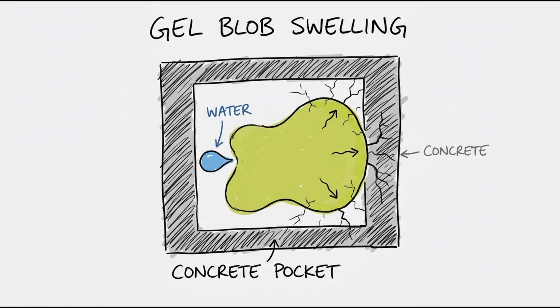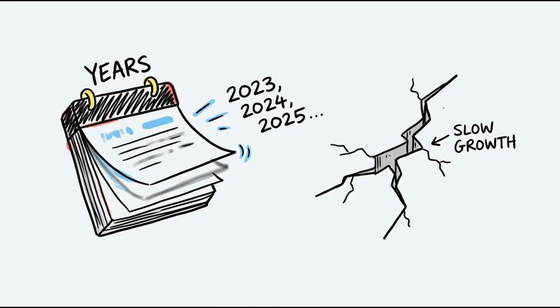Here's where it gets nasty. That gel absorbs water and swells. Trapped deep inside a solid concrete slab with nowhere to expand into, the swelling gel generates enormous internal pressure, enough to physically crack the concrete from the inside out, one aggregate particle at a time. The damage doesn't show up overnight. ASR is a slow-motion process, often taking years or even decades to become visible. And when it finally does surface, it leaves unmistakable fingerprints.